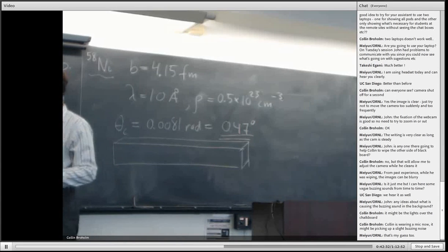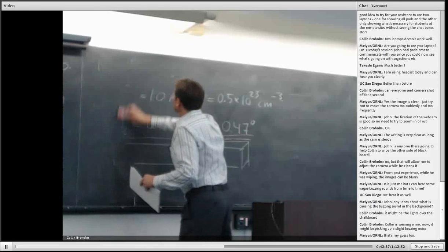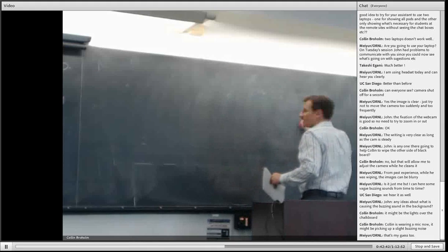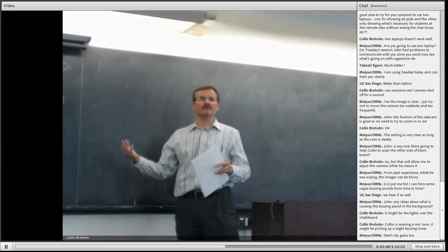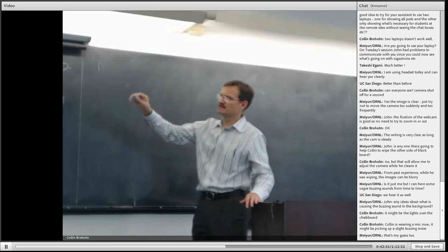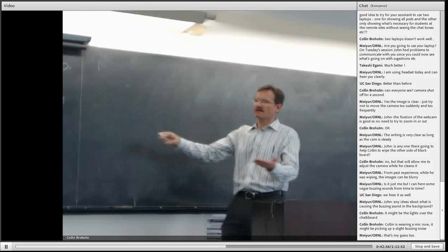I've got various things we could talk about, and I'd like to say one thing more about this total external reflection process, and tell you about a very elegant experiment that is used to actually measure these scattering lengths. You might say, well, if you can't calculate them, how are you going to actually measure those things? And of course, we have now shown that the scattering length is directly related to the critical angle for total external reflection. So there's an experiment you could do: see when you reach that critical angle. And that is a way of doing it.